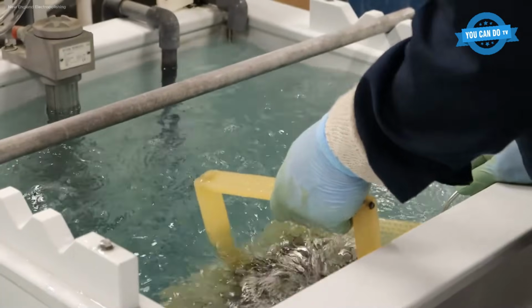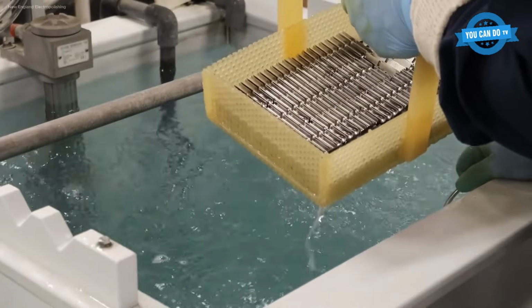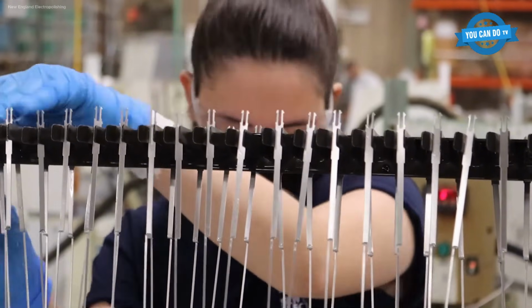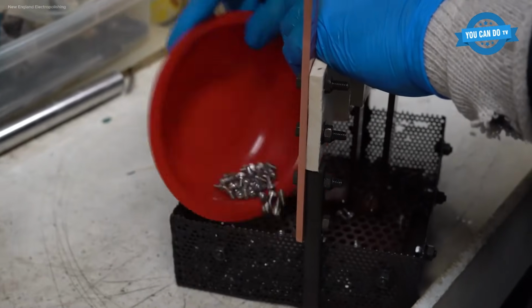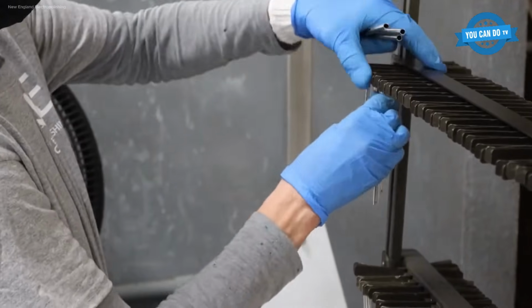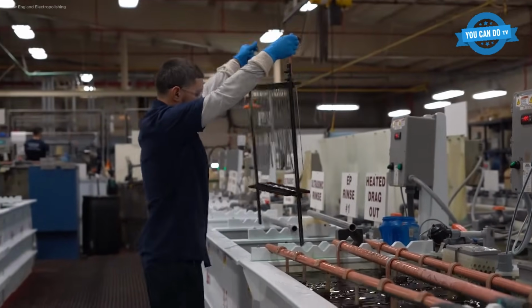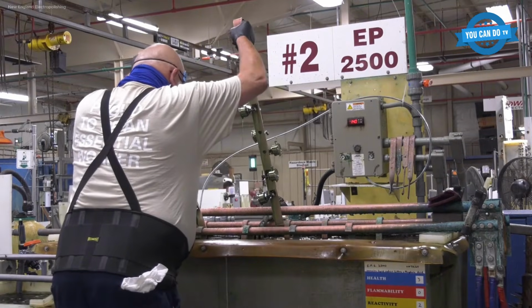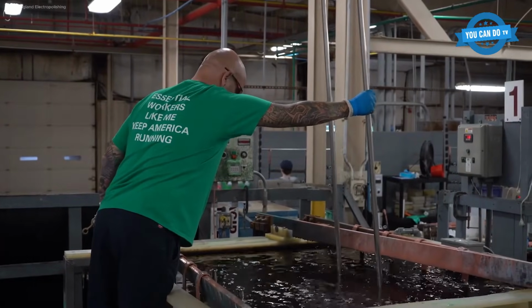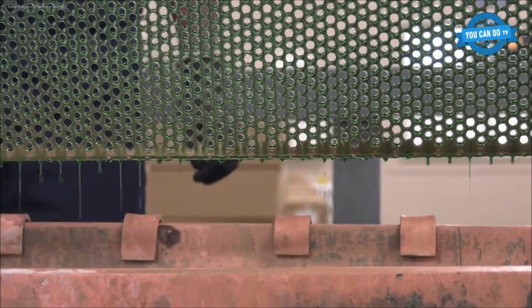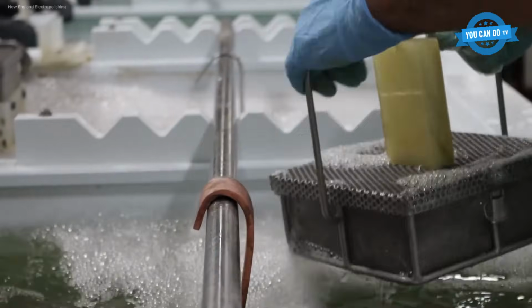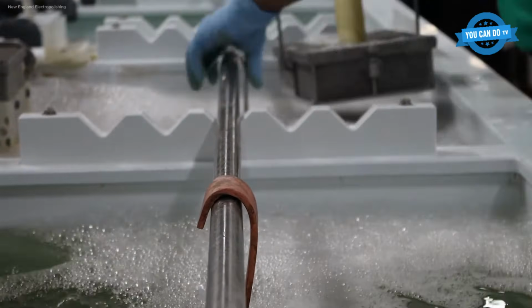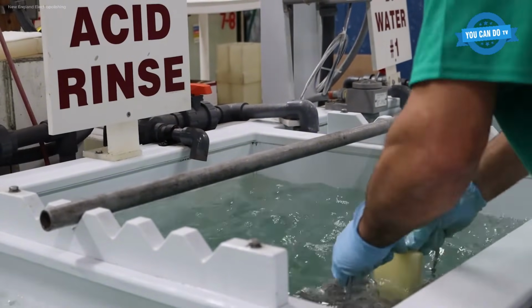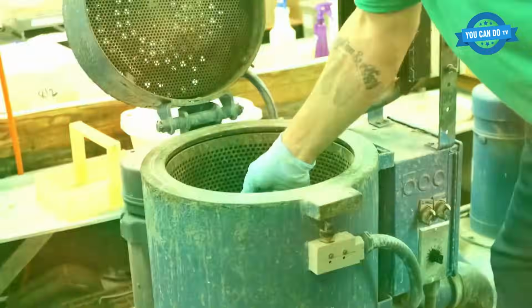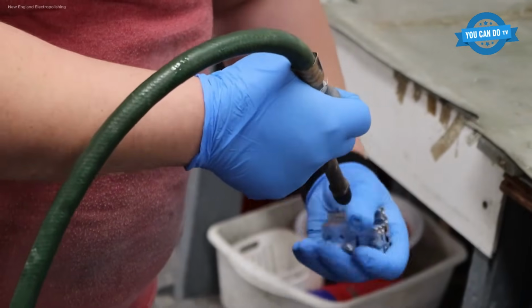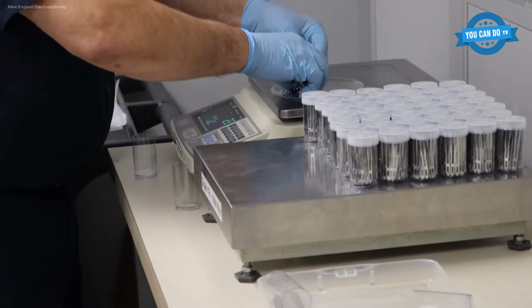Electropolishing is a precision electrochemical finishing process that removes a thin layer of metal from stainless steel surfaces, enhancing both functionality and appearance. This controlled removal eliminates microscopic imperfections, sharp edges, and embedded contaminants while simultaneously passivating the surface. The operation commences with pre-cleaning to eliminate machining oils and residues, followed by immersion in an electrolyte bath, typically a blend of sulfuric and phosphoric acids. A positive current is applied to the part, the anode, while negative cathodes facilitate ion removal. This results in a microscopically smooth, corrosion-resistant, oxygen-enriched surface ideal for critical industries like medical, food, and aerospace.